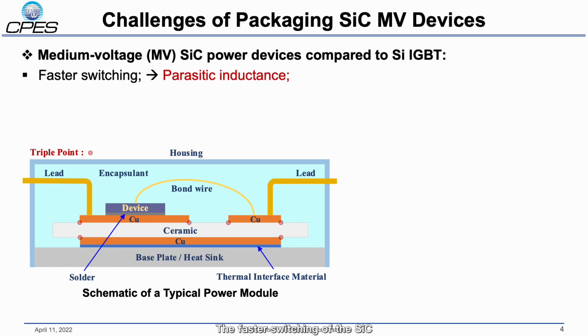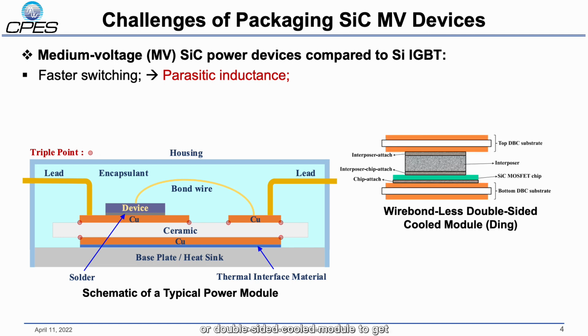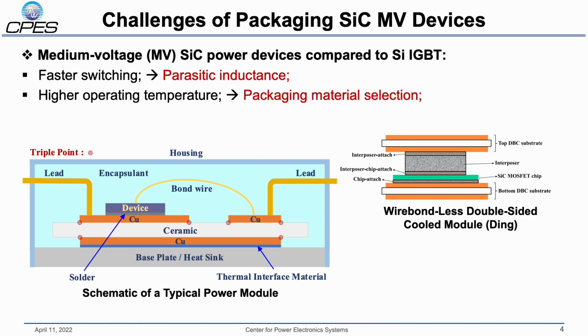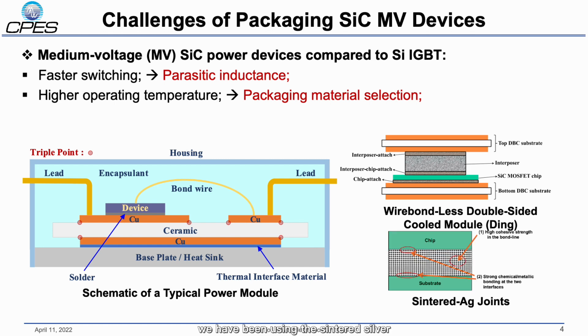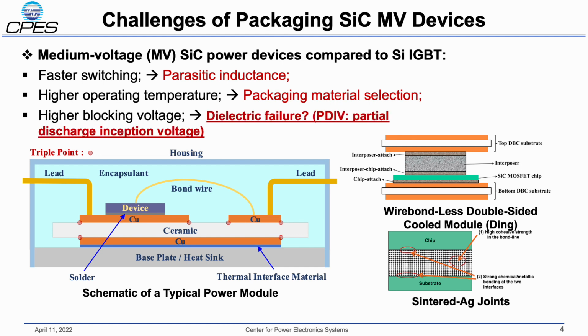The faster switching of the silicon carbide medium voltage power devices requires interconnects with lower parasitic inductance. People use wire bondless or double-sided cooled module to get rid of the thin wires to significantly reduce the parasitic inductance. The higher operating temperature requires more stringent material selection, especially for the die attach. During the last 20 years, we have been using the sintered silver to replace the traditional solder. The melting point can go up to 960 degrees C. It also has much lower electrical and thermal resistance.